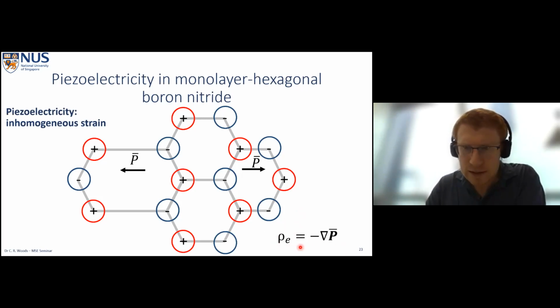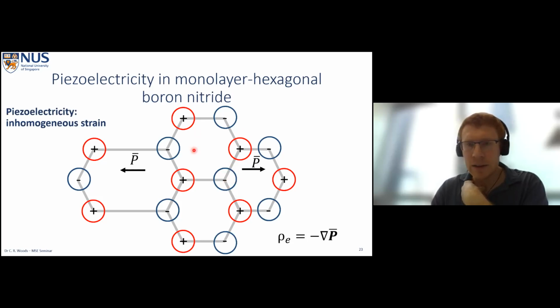And if this doesn't seem intuitive to you, then you can think of just about counting charge here. So if I separate the sample along a line somewhere like here, you can see on the left-hand side, we have 2 positive charge, 1 negative. So we would have, say, an effective positive charge on this side. And then over here, of course, we're going to have 1 more negative charged atom than positive. So we produce a negative induced charge over here. So this is a sort of simplistic way to think about this induced charge.